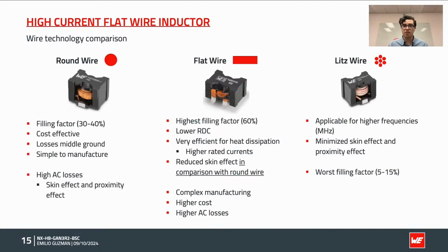Now, as a comparison between the three wire technologies, we can see the round wire, the flat wire, and the litz wire. For the round wire, the filling factor is about 30 to 40%. It is cost effective. The losses have a middle ground, and it's simple to manufacture as the round wire is more readily available. Although it has higher AC losses, being the skin effect and proximity effect, as we just saw before. For the flat wire, it has the highest filling factor of up to 60%. It has the lower RDC. It is very efficient for heat dissipation with higher rated currents. And it has reduced the skin effect in comparison with the round wire specifically.